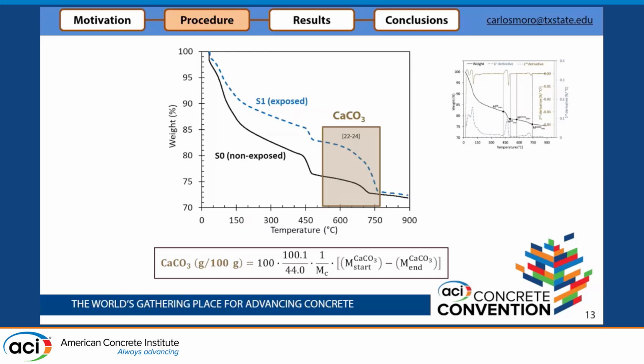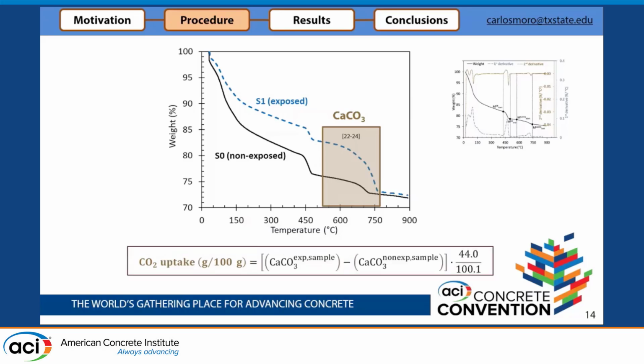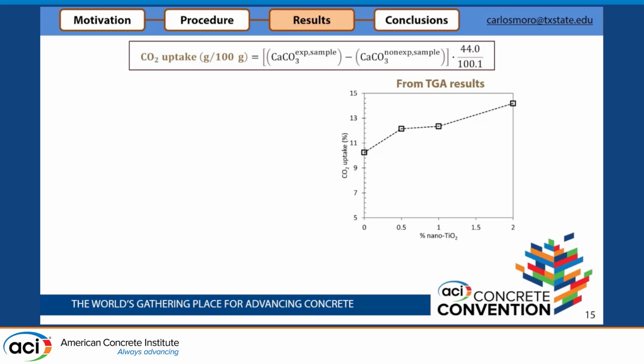And we used the first derivative and the second derivative to be more precise on this. What I mean is that we didn't use strictly 550. It was different in every single sample because the TGA curves have different shapes. And basically we can then multiply to obtain the CO2 capture, based, as I said, on the exposed minus the non-exposed sample. And the results show that increasing the titanium dioxide percentage also increases the CO2 capture. That means that it's going up and up, even though the compressive strength didn't increase that much. Okay?